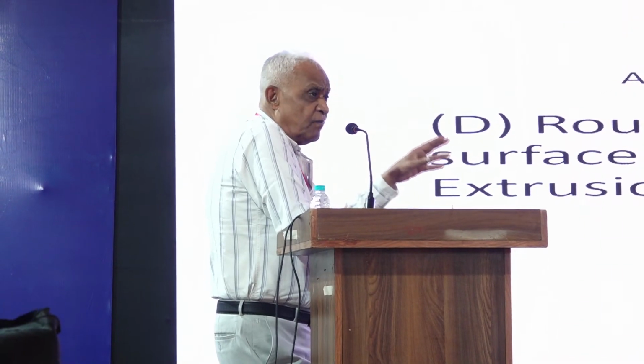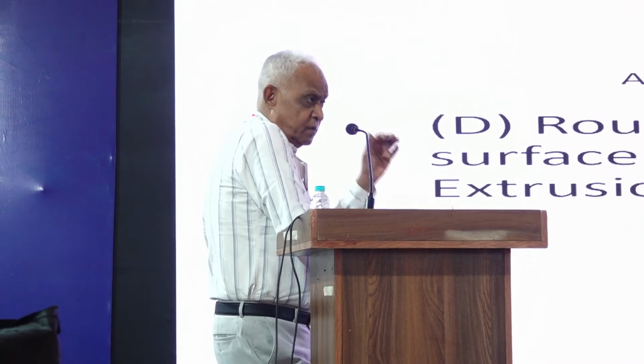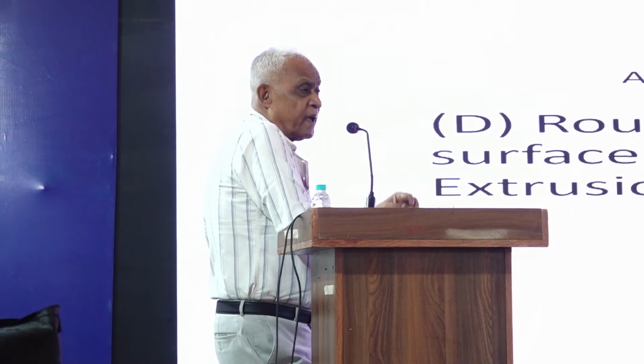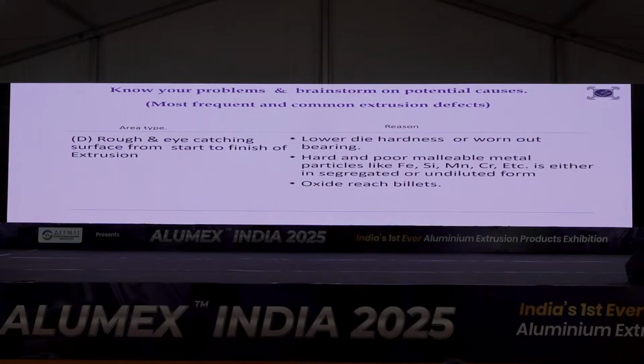So if it is very rich in ferro elements and becomes more magnetic, and we all know when we extrude, there is serious friction between die and aluminium. Any friction will create static electricity, and it will form a temporary magnet that gets stuck on the die, just at the drop area of the exit. That gives the most serious roughness problem. Oxide-rich billet is another contributor.